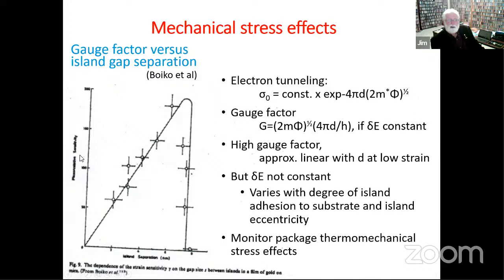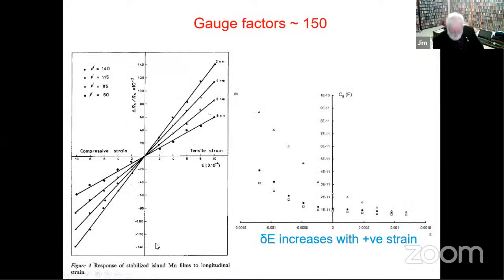And so the gauge factor, which is plotted here as a function of the island separation on the x-axis, is a linear effect. But then the secondary effect of the activation energy starts to affect things, and you get this turnover. So this can be used in a package to monitor thermomechanical stress effects. A gauge factor is around 150 on this figure here, which is the strain variation of resistance. Also, the activation energy here, because that's related to the capacitance, varies with the strain. So this is showing that the activation energy can.